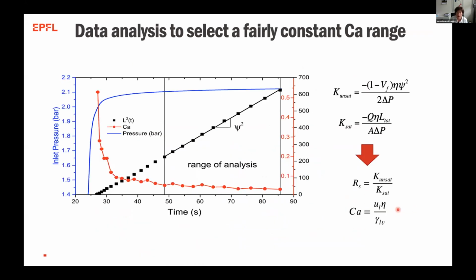Another problem is that if you have a constant pressure experiment, the capillary number actually changes with time because the velocity is not constant. So we found a range of analysis where the capillary number remains more or less constant after the beginning of impregnation, in this range.